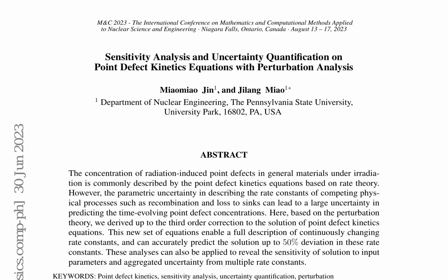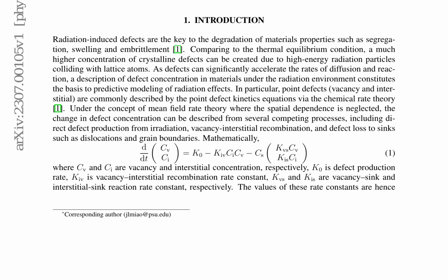To address this issue, the authors employ perturbation theory to derive up to the third-order correction to the solution of point defect kinetics equations. This new set of equations enables a full description of continuously changing rate constants and can accurately predict the solution up to 50% deviation in these rate constants.